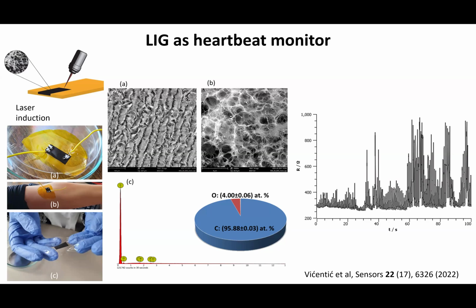If you zoom out a little bit, shown in part A, you can see these lines from raster scanning the laser. We first made just rectangles, 2 by 1 centimeter, shown on the left, on this yellow Kapton substrate. We just very crudely put 2 electrical contacts on this rectangle, and we found that this material is extremely piezoresistive, which means that if you bend it just a little bit, the resistance that you measure across these 2 terminals changes dramatically. And it's so sensitive that if you attach it to the forearm of a person, like on the vein, you can register the pulsing of the vein in real time.